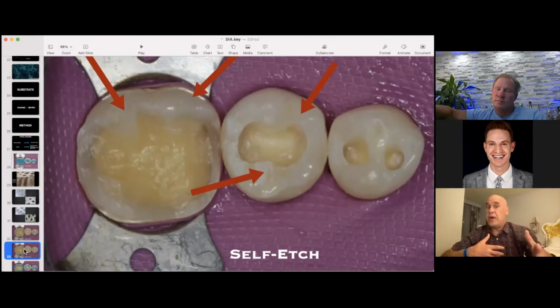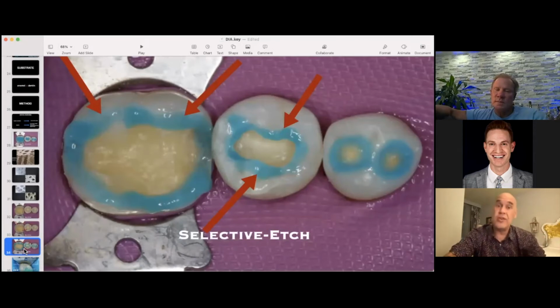So if you want to go the total etch route, that's fine. If you want to go the self-etch route on dentin, I will highly recommend that you do this. Okay, it's called selective etch. Now you have the best of both worlds. You have good bond to enamel because you have etched it with phosphoric acid. And now you have, I don't want to say protection of the dentin, but now you're going to avoid the possibility of post-op sensitivity by self-etching dentin.